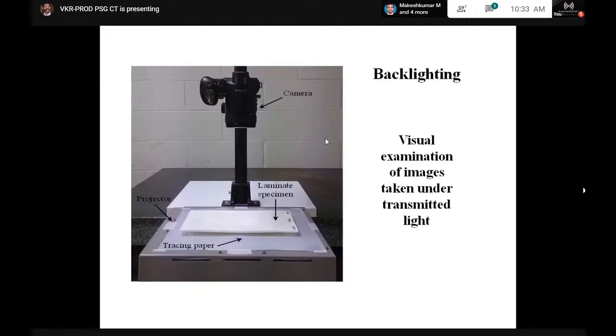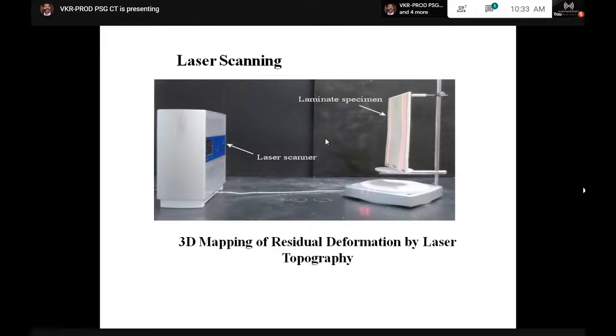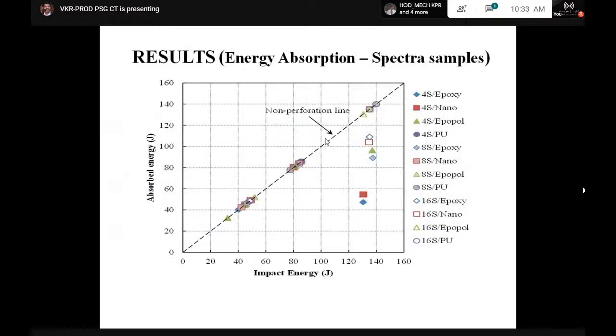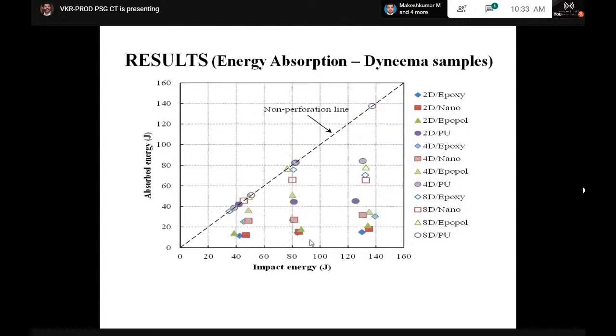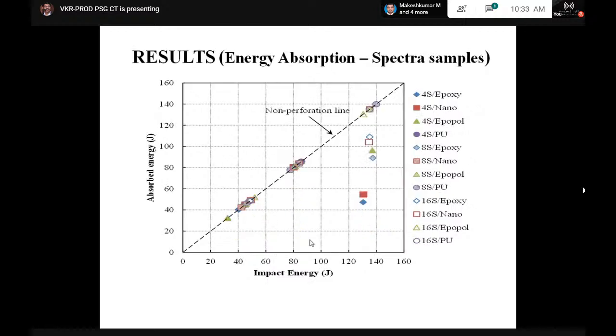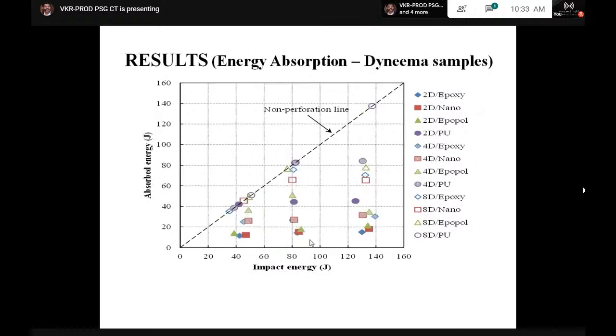This is about the backlighting. The specimen is placed above the projector and recorded using a camera. Laser scanning is a 3D mapping of residual deformation by laser topography. These are the results of the Spectra samples, where you can see the absorbed energy versus impact energy. This is in comparison with Dyneema. The other one is Spectra, and Spectra really performs much better than Dyneema.